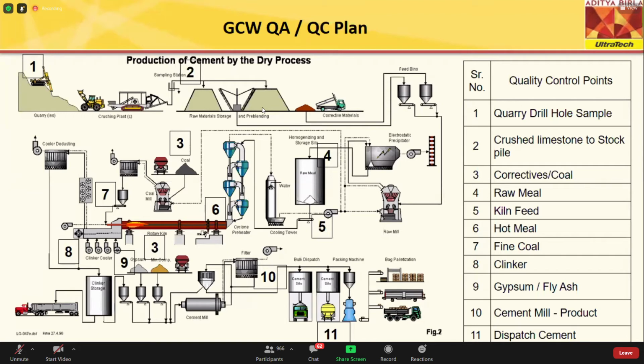Parallelly, we test the material in XRF, again a very sophisticated machine which analyzes the material within a minute and tells us the percentage of different components in the mix, so that the desired quality raw mix is prepared and stored in the raw meal silo.